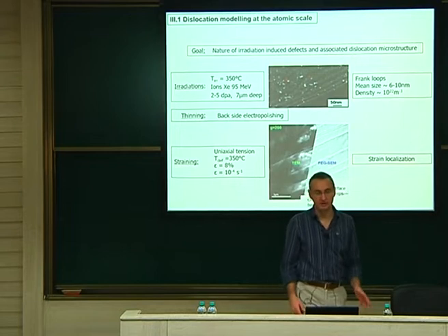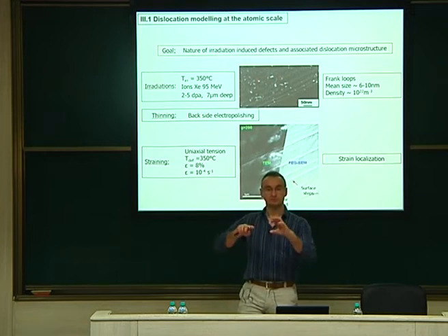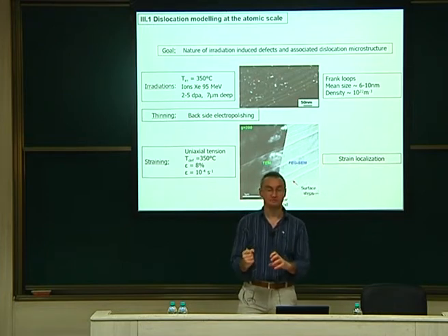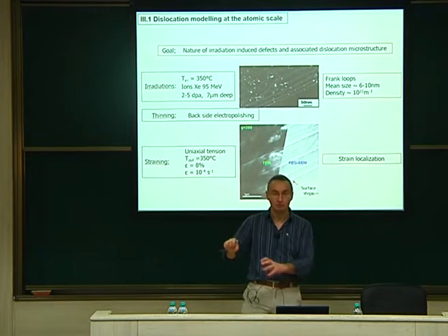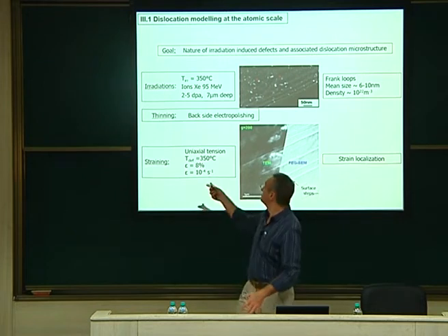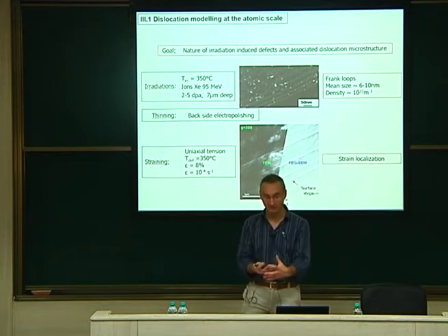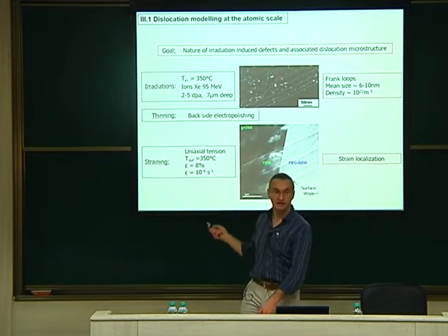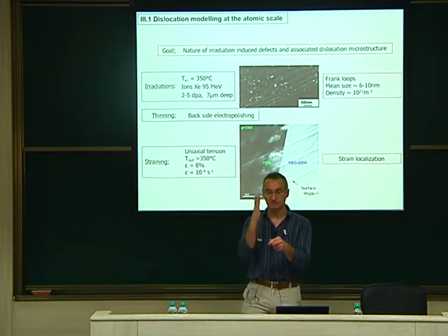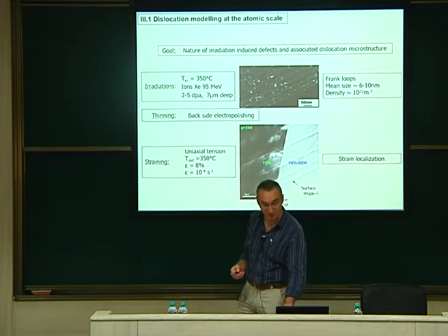This is what happens more or less in reality. In reality, if you have stainless steel, which is, for example, used for the screws to attach your shield in your material, then there is some force when you put your screw like this, you put some force inside. So there is an internal force that you apply. Your material is now irradiated. So this force is applied on your dislocations and your irradiation defects. So this can create some plasticity. And sometimes you can see that these screws are broken after a few months of service. It could be broken just because of this localization. Okay. So this is really something which is important.